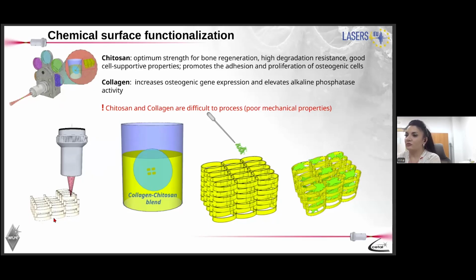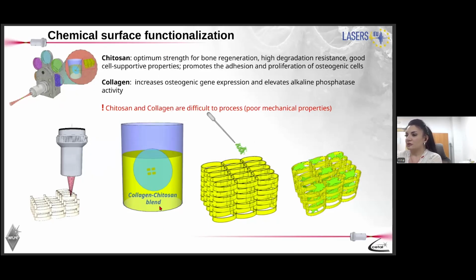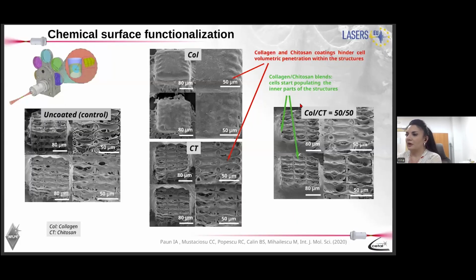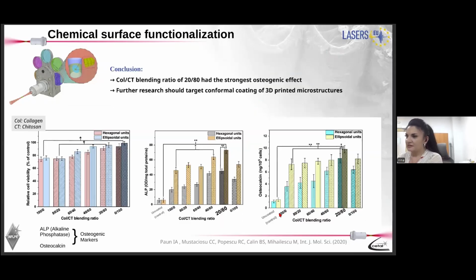Instead, we made the backbone of the structure with a commercial biocompatible photoresist, as we did before, and we coated these structures by immersion in collagen-chitosan blends. And we saw what happens with the cells that were seeded on this coated structure. I will not stay too much on this part because there is much room to improve here regarding cell attachment, but I will tell you that we tested different blending ratios between collagen and chitosan. The same test with the osteogenic markers as before, the two ones here. And we found that the best results from the point of view of bone regeneration, or at least bone formation, were obtained for a collagen-chitosan blending ratio of 20% to 80%.